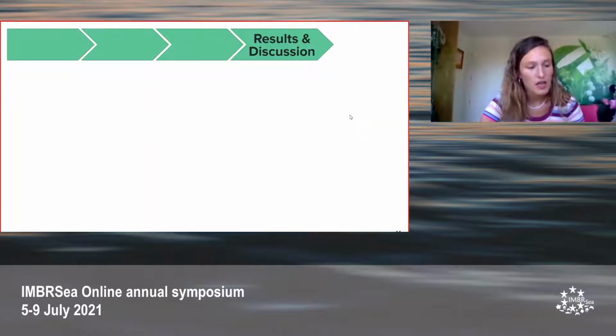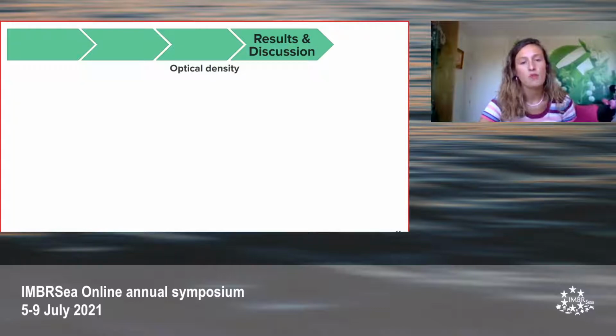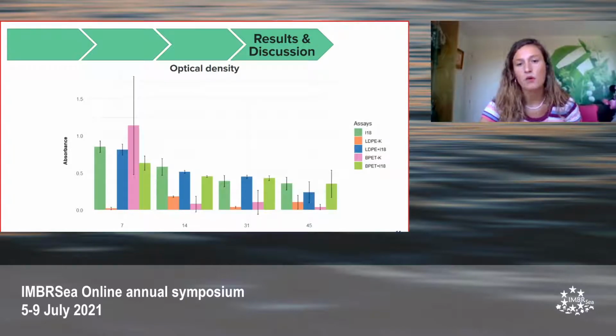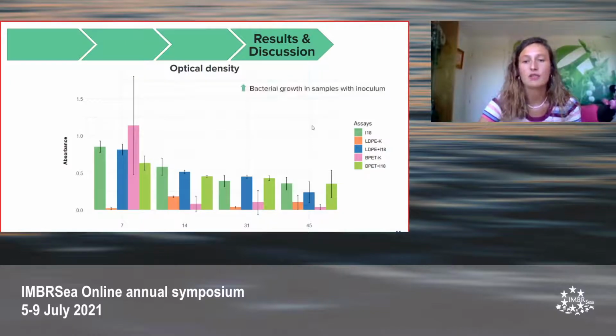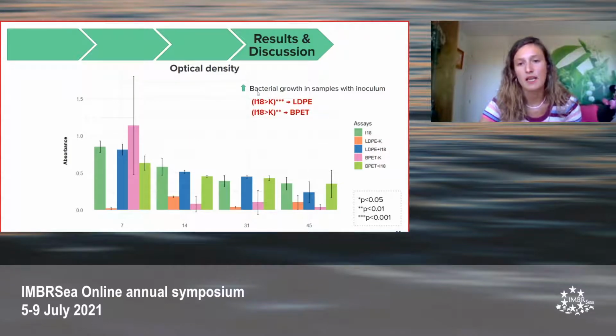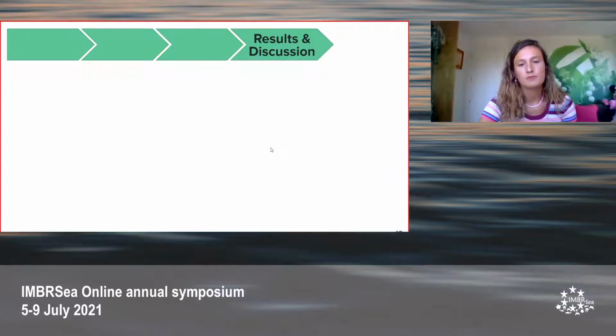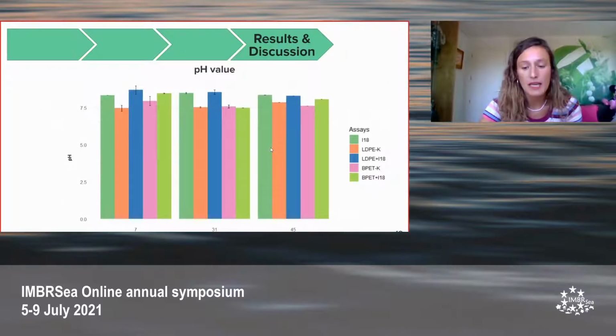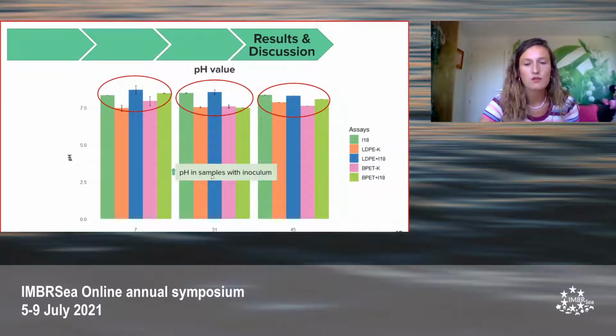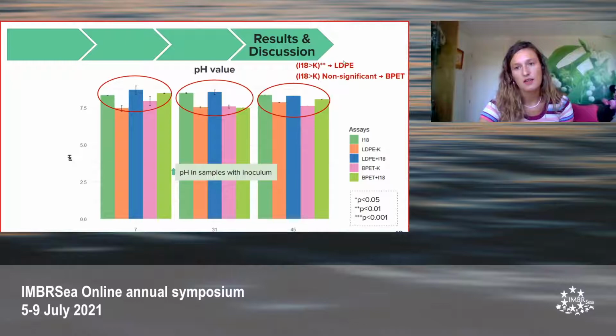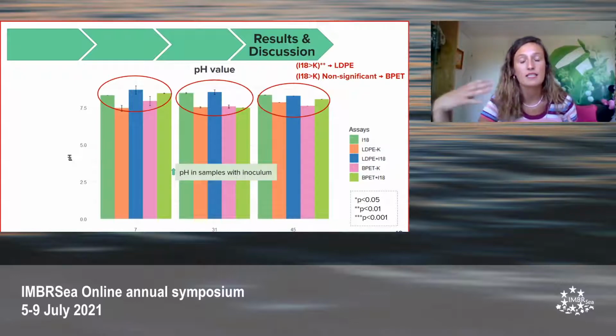Moving on to results, the first variable measured was optical density, where we obtained what we were expecting, a higher bacterial growth in samples with inoculum. And for both polymers, we obtained statistical differences. For the pH, similar results were obtained, in which higher pH was observed in the samples with inocula, and statistical significance was obtained only in low-density polyethylene. This is important because it's indicative that bacteria require certain alkalinity in the medium to act and to biodegrade the